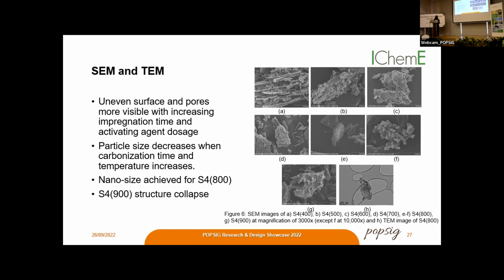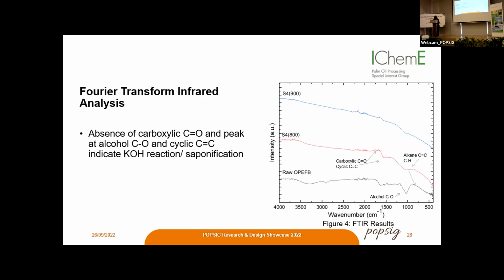However, after the optimum temperature, the structure will tend to collapse due to over-carbonization. So this is why at 900 degrees, the pores were observed to have collapsed. Next is the Fourier transform infrared analysis.